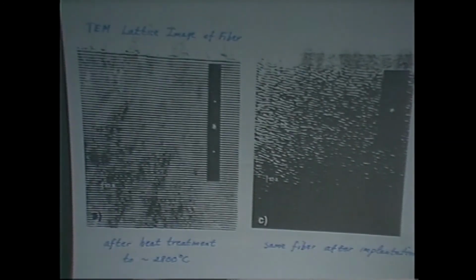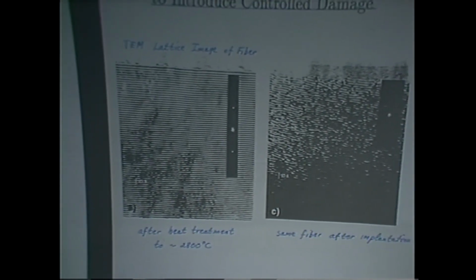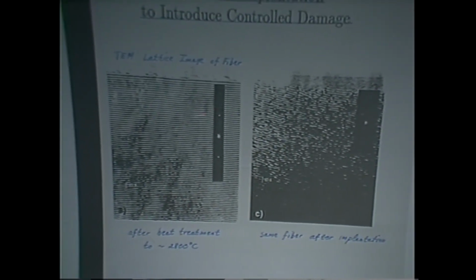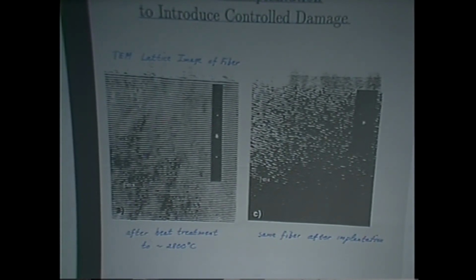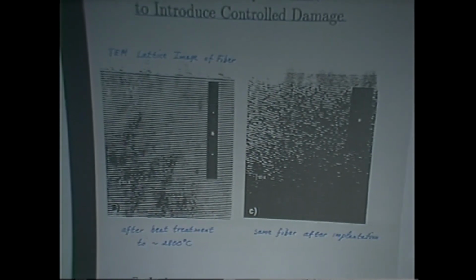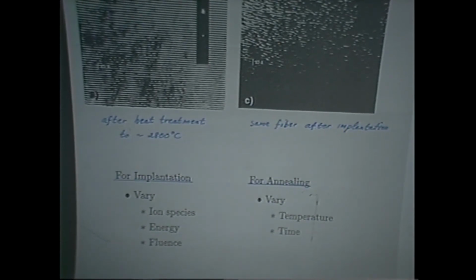So we started working on carbon fibers. Well, actually, when you heat treat these things, you can make them almost like single crystals. And here's a transmission electron microscopy picture of one of these vapor-grown fibers. And these are the lattice planes separated by 3.5 angstroms. It's really quite wonderful. Once we were able to accomplish that, we decided, well, this is a nice engineering project. We can mess up this lattice and see how it regrows. So we got into the business of ion implantation, where we could vary all the different things that you can vary in implantation, the species, the energy, the fluence, et cetera, and then anneal the samples, varying the temperature, the time, and do material science on this.